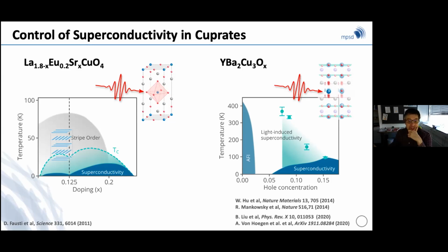This is an example which is not intellectually particularly challenging, yet technically difficult to do, in which we showed that if you melted the stripe order that suppresses superconductivity, we could induce a quasi-metastable superconducting state at temperatures far above the thermodynamic transition temperature. And more recently, in other systems such as YBCO, we showed that by modulating certain atoms, we could induce coherencies that look like superconducting coherencies, up to temperatures that exceed room temperature, and in fact, throughout this mysterious pseudogap region that is found in the underdoped side of the cuprates. Again, this is not what I will talk about today.